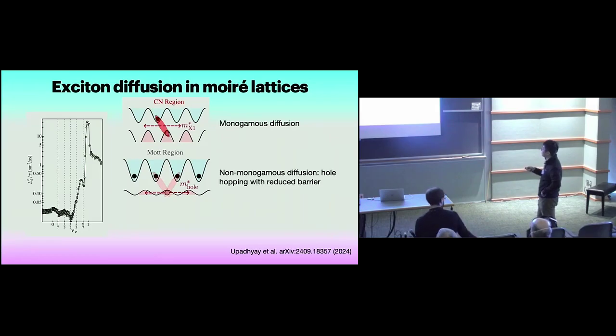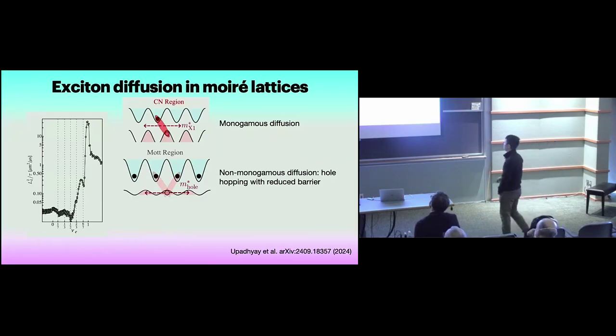What makes this interesting is that now I don't need the whole exciton to diffuse. Actually, the whole exciton as a collective particle doesn't want to diffuse because it will double occupy this site, but only the hole needs to turn on in order for the emission to be diffused to a different region. So you have a reduction in the effective mass, right? You just have half of the particle to diffuse. And also because I have electrons here, it makes the hole more likely to go into this intermediate state. In other words, it reduces the effective potential because the electron is right in the middle between these two hole barriers. So you have two effects that help to promote the diffusion of excitons in such a system.